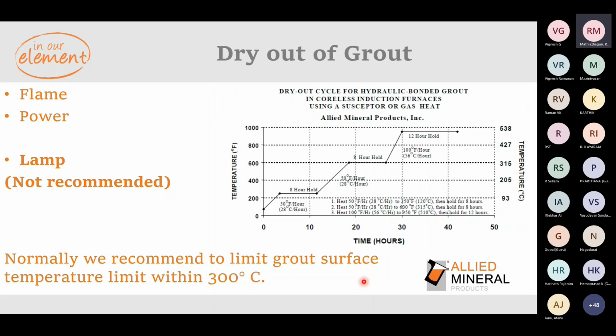So when it comes to the dry out of grout, drying of grout is one important step when you try to maximize the refractory lining life. We recommend to do the dry out either by flame or power. Burner is most preferable. Heating through a halogen lamp is not recommended, even though commonly everyone follows this. So we don't recommend drying of grout with a halogen bulb.